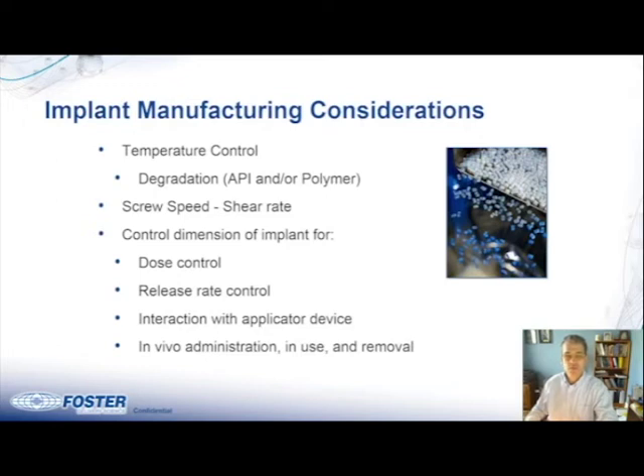The screw speed will influence the highest shear rate that the formulation experiences in the process. Shear rate will influence both temperature rise and viscosity of the material in the process. It's important to control the dimensions for release rate control, since the surface area can have a strong effect on this release rate. Dimensions of the implant also influence how the implant will interact with the applicator device and affect in vivo administration, both in use and removal. Typically, multi-axis laser micrometers are used to control the dimensions of the implant.